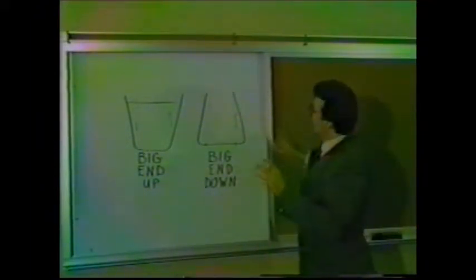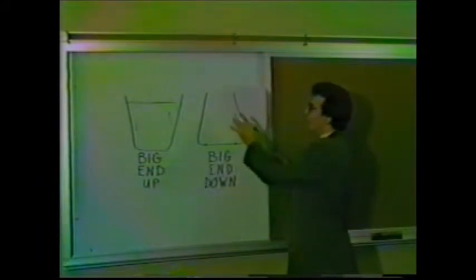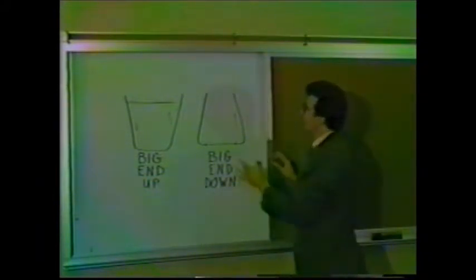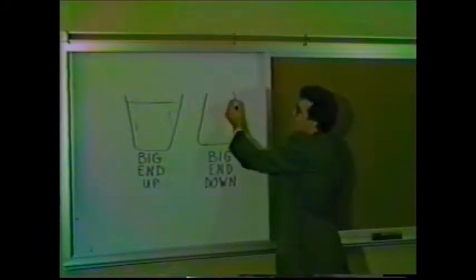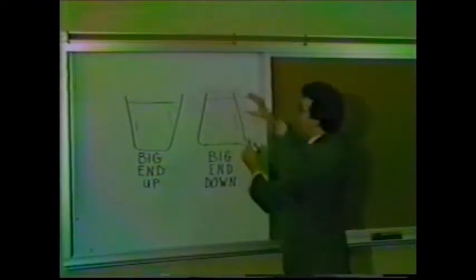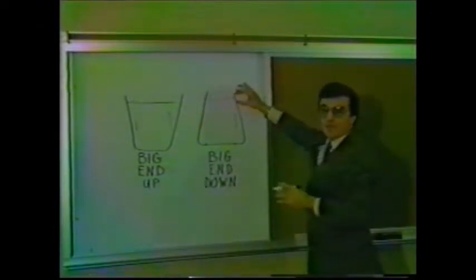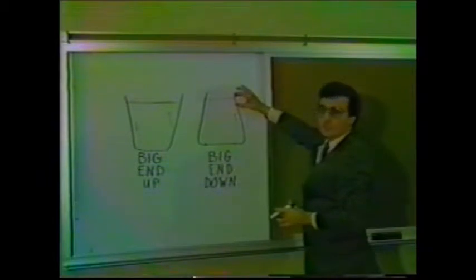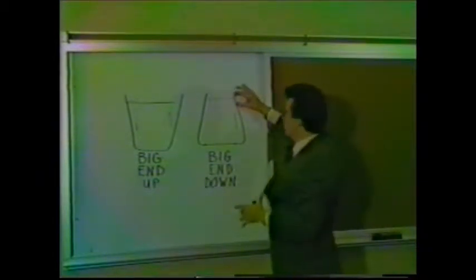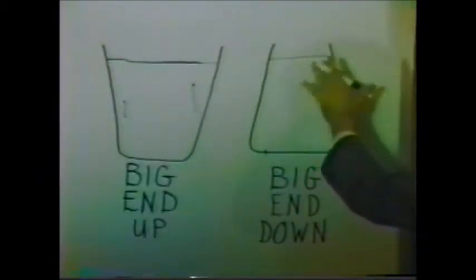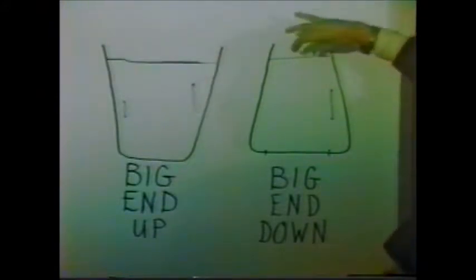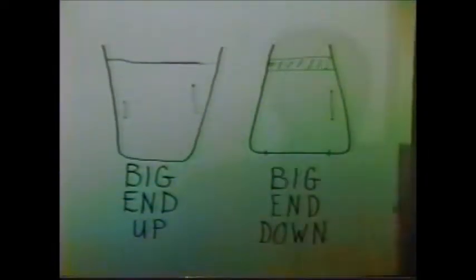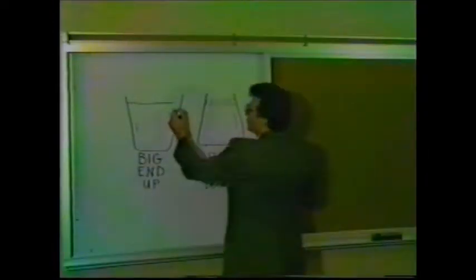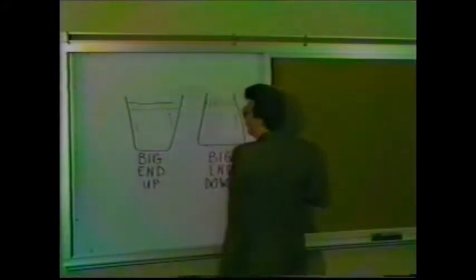Also, something that contributes to a lower cost of a big end down mold is that after filling the steel up, they normally have to discard a certain amount of the steel that is unusable for hot rolled bars. Because there is a smaller area up at the top of a big end down mold, there is obviously less volume of steel that would have to be thrown away and recycled, as opposed to a big end up mold.